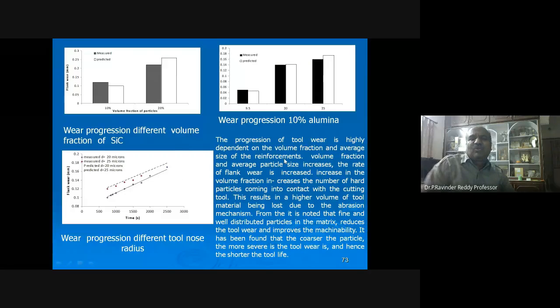The progression of the tool wear is highly dependent on the volume fraction and average size of the reinforcements. As volume fraction and average particle size increase, the rate of flank wear is also observed to increase. The increase in the volume fraction increases the number of hard particles coming into contact with the cutting tool. This results in a higher volume of tool material being lost due to abrasion.